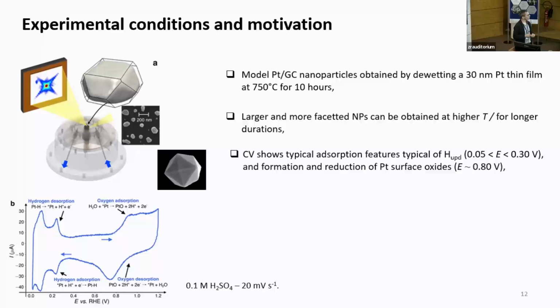Now, there was a comment about the movement. I'm mostly convinced that the interactions we have with the support are very weak. So maybe you won't see this change in equilibrium shape because the interactions are very weak. This is very different from, for example, gas phase catalysis, where particles sit on metal oxide and have very strong interaction with the support. Here we are mostly in the range of van der Waals interaction, and this is the reason why the particles are moving here and not in gas phase catalysis. Marie-Ingrid's group is doing gas phase catalysis as well, and they do not suffer strongly from these changes in particle location.